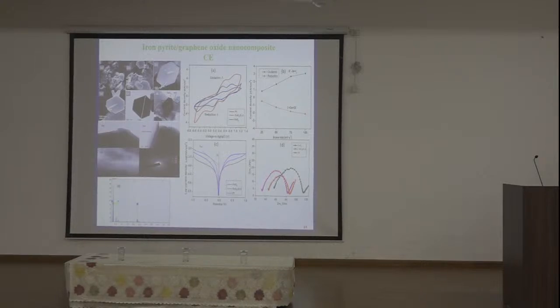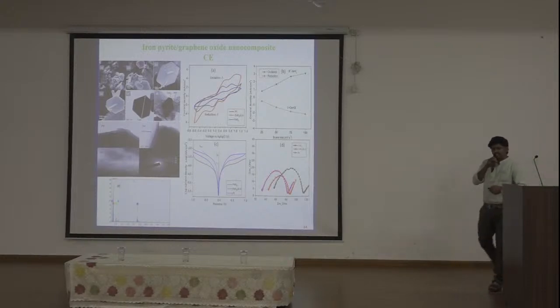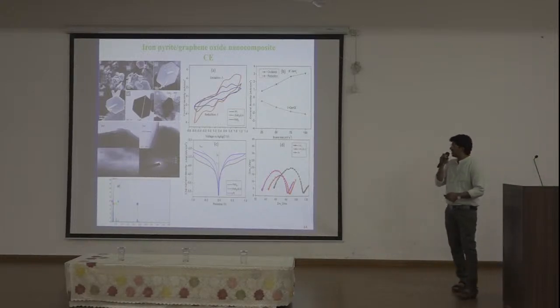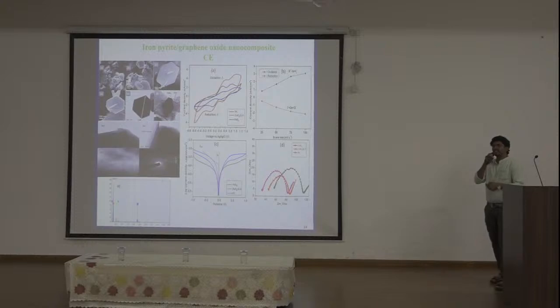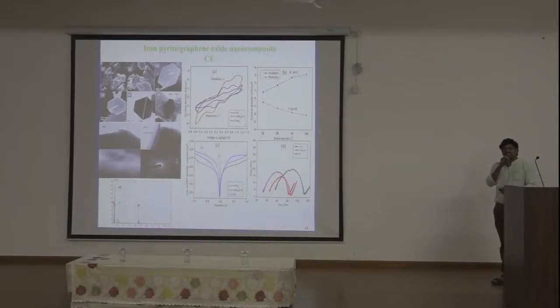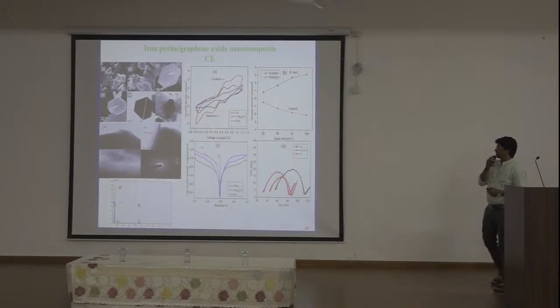So reduced graphene oxide is not only providing more active sites to enhance the electrocatalytic activity, it is also increasing the electrical conductivity. That's why we have seen this reduction peak at a lower potential. This is also helpful to increase the fast regeneration in the DSSC. And this is also the same thing.